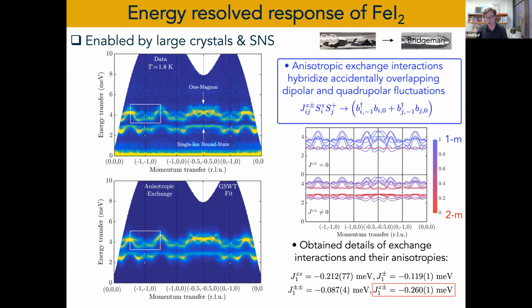So the primary signature of the anisotropic interaction is the tilting of the spin plane with respect to the triangular plane. And 10 degrees is, sensitivity-wise, sometimes difficult with diffraction. So it's natural that people did not realize this, but we are after it. Thank you.